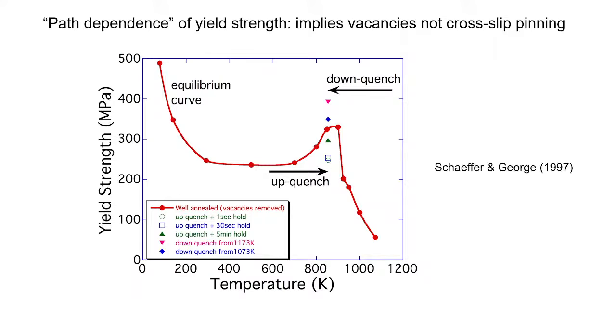So when you up-quench very fast, you get very low yield strength. You up-quench, and then you hold for a little bit longer, the yield strength goes up. You hold for a little bit longer, and then you get vacancies, which is representative of where you quenched it from, and so on and so forth.